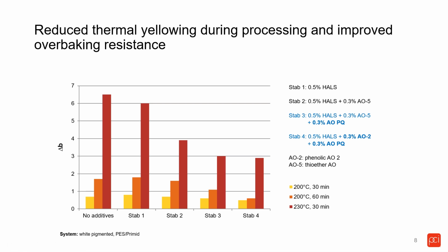Here is another test we have done. As I mentioned earlier, we can do the standard baking temperature at 200 degrees Celsius for 30 minutes, and we have two types of overbaking test: 60 minutes at the same temperature, or 30 minutes at 230 degrees Celsius. There is definitely quite a significant difference between the different stabilizers. In this case, we also added the HALS, a component that will be used in powder coating formulations. We want to see the effect of a phenolic antioxidant, a thioether antioxidant, and then the phosphorus-based, phosphite-based antioxidant, which is the PQ.